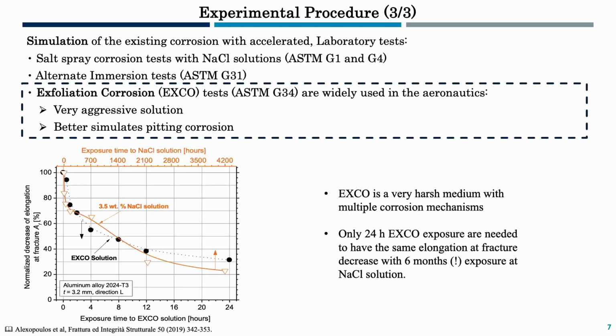The EXCO solution was selected because it is a widely used solution for the simulation of corrosion in aeronautics, because it is a very aggressive solution and better simulates the pitting attack. And also in a previous investigation of our team, we noticed that, for example, if we compare the EXCO solution with the 3.5 weight percentage sodium chloride, only 24 hours exposure to EXCO are needed in order to have the same degradation of elongation at fracture as 6 months exposure to the sodium chloride solution.